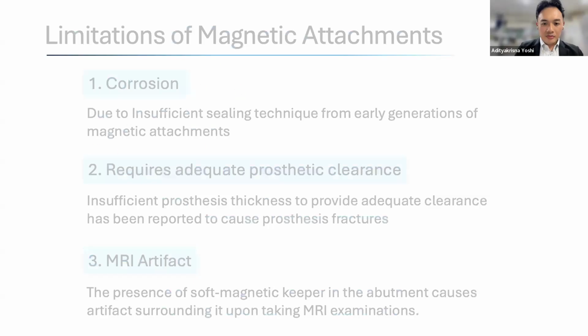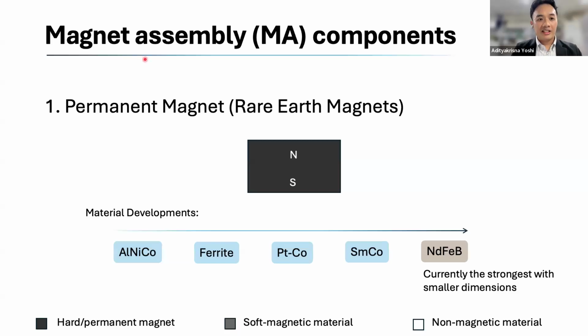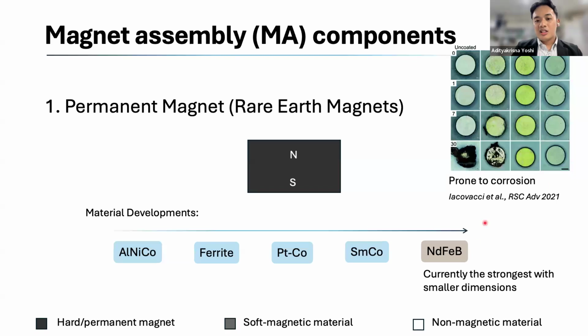Regarding the first problem, I would like to introduce the development of the magnetic attachment. Remember the magnet assembly, the upper component that contains the permanent magnet that provides magnetic force and is cemented inside the prosthesis structure. It consists of the core component called the permanent magnet, mainly composed of rare earth magnets. In the initial periods, magnets such as aluminum nickel cobalt, ferrite, platinum cobalt, or samarium cobalt were utilized. However, they had bulky structures and weak force. With the innovation of neodymium iron boron, a strong and thin magnet can be achieved.